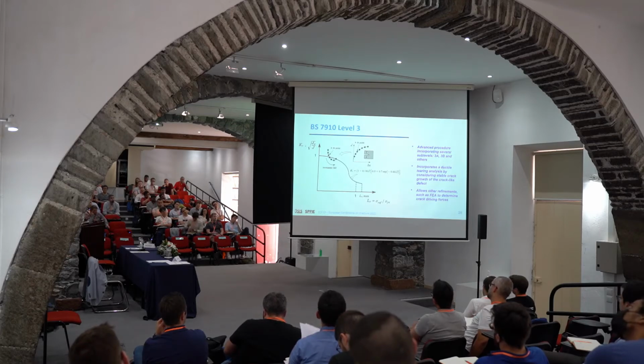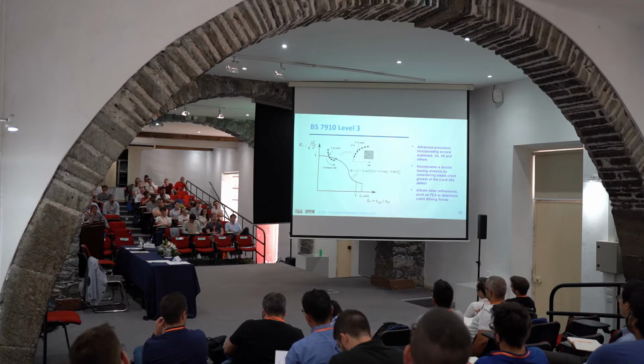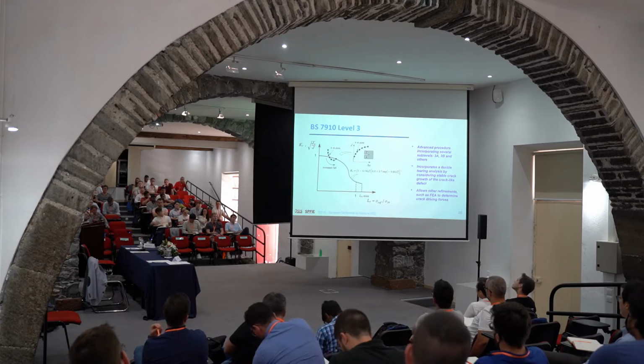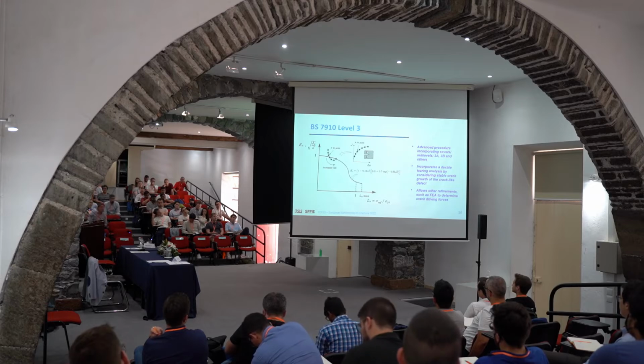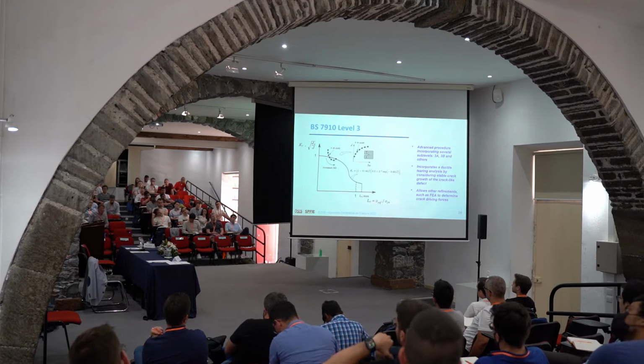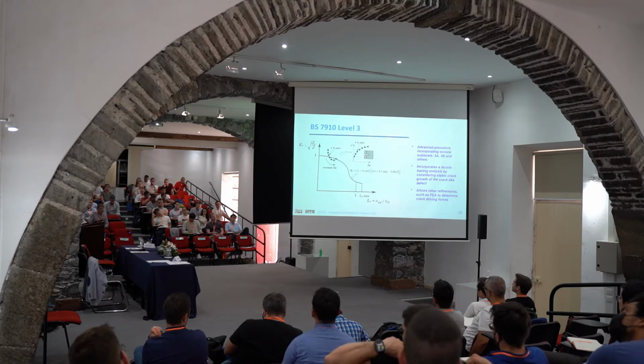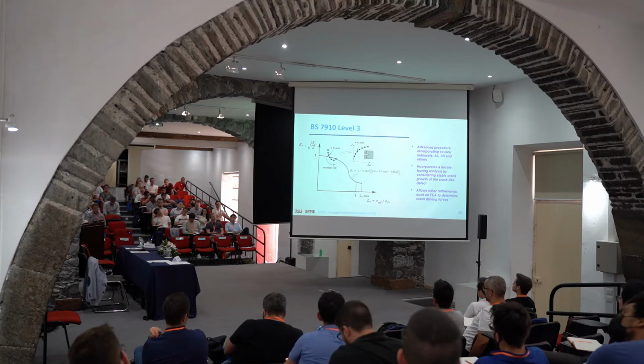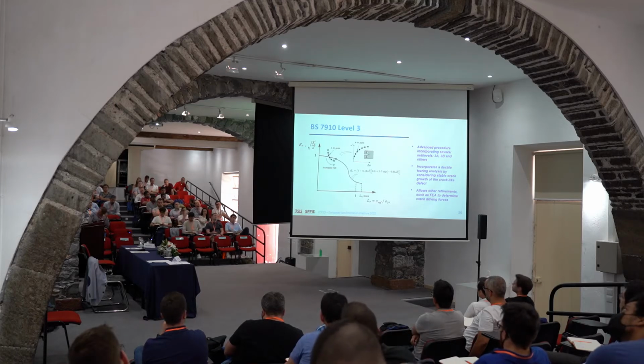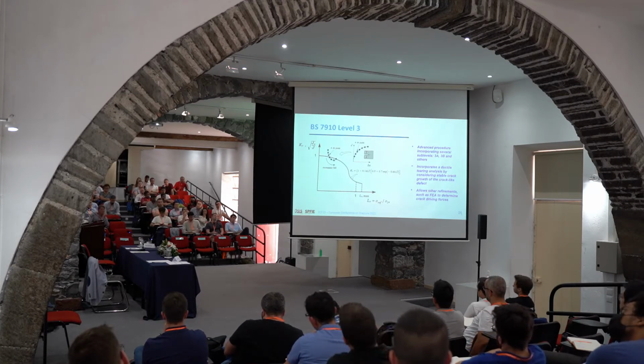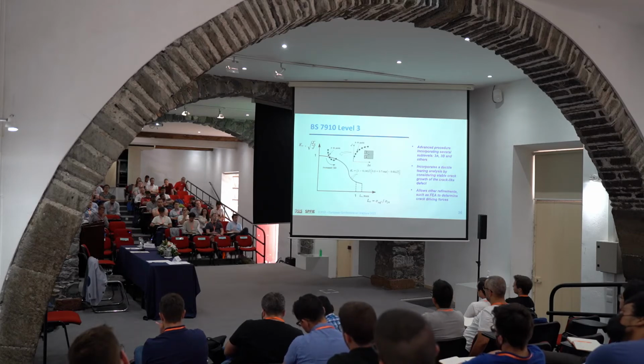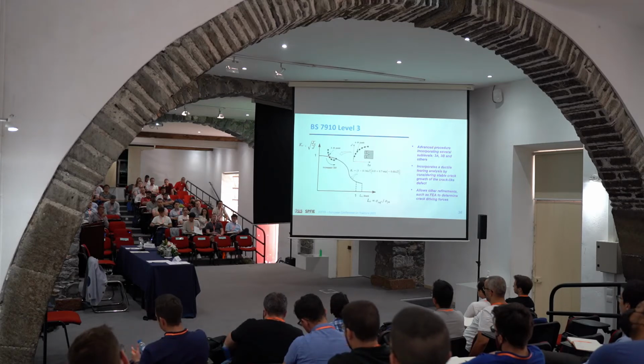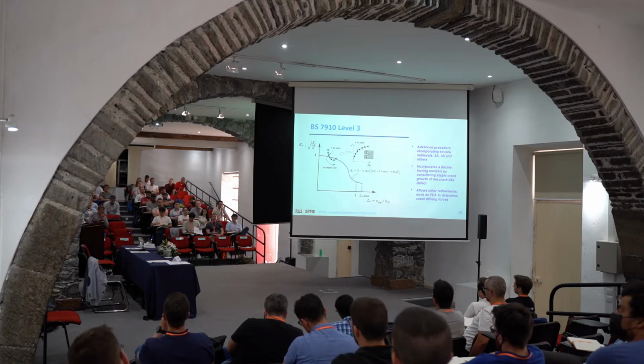As I told you, as we increase the level, okay, the analysis is more accurate. It's good, but then I need more data, more experimental data, more knowledge about the loading. And also, level 3 enables using a ductile tearing analysis. Okay? Because again, in the real world, when you find a crack, the crack does not always stay at the same place, the same size, static.